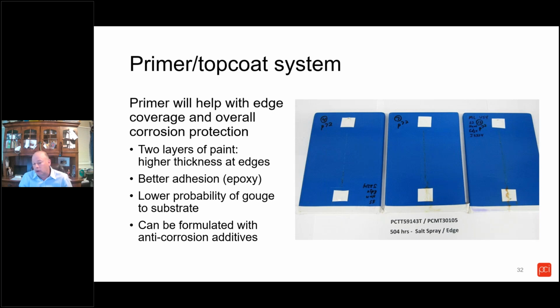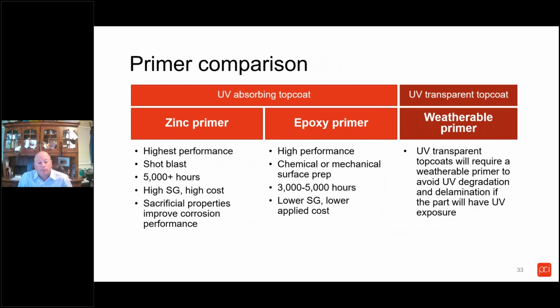There are different primers you can look at, and different primers can be formulated for better corrosion protection. Probably the most common is zinc primers. Zinc has sacrificial properties—corrosion will attack the zinc before the substrate, prolonging the life of that substrate. We generally recommend shot blast preparation on the substrate, which gives you your best results, and in that situation we can see 5,000 plus hours of salt spray protection.